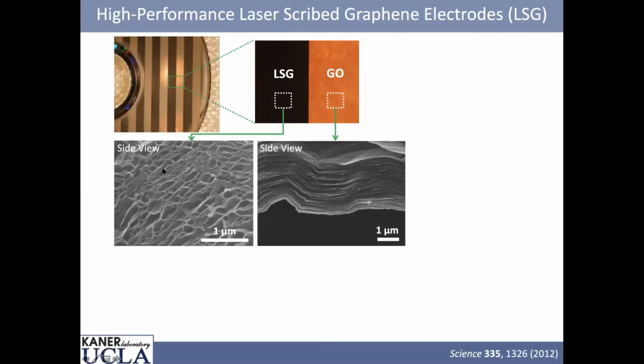Now, this is our form of graphene. It's completely different than what Novoselov and Geim are making. Novoselov and Geim with Scotch tape are making the world's best graphene. We're making the world's most defective graphene. But if you're going to do energy storage, this is exactly the structure you want. And the reason is you need a structure that's incompressible and you can address all surfaces.